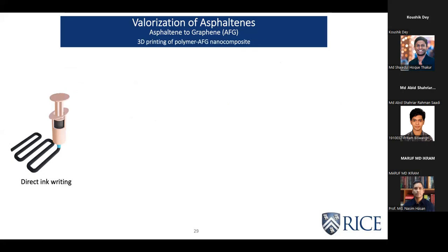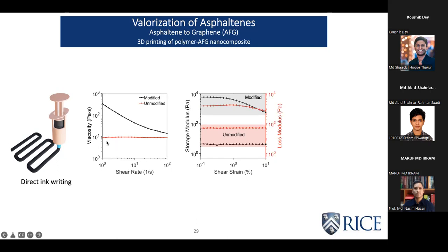Our group works a lot with additive manufacturing, and I have also been working with additive manufacturing. So we thought that if we can 3D print these polymer-AFG nanocomposites, one of the techniques that we use is known as direct ink writing. It's an extrusion-based technique. In order to print any material using this technique, the material needs to show some very specific rheological properties. However, for the pristine epoxy AFG nanocomposite, we could not see those desired rheological responses. As a result, we had to add a rheology modifier, which in this case was fumed silica. So after we added the minimal amount of fumed silica, we could obtain the proper rheological response.